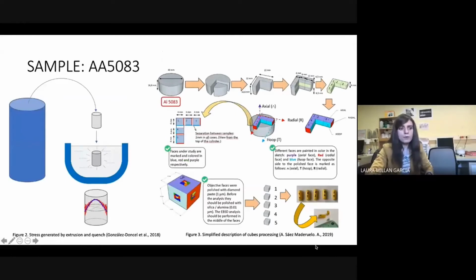For this work, we are focused on an aluminium alloy named AA5083. This alloy is composed of a matrix of aluminium and other elements, fundamentally magnesium. We prepared a cylindrical aluminium sample from an extruded bar. This sample is heated at 530 degrees and is quenched in water. This treatment generates residual stress inside the sample. In a second step, we extracted cubes from the center and at 6 and 12 millimeters along the diameter of the cylindrical sample.